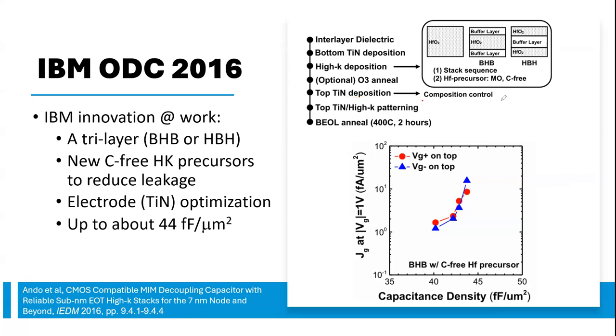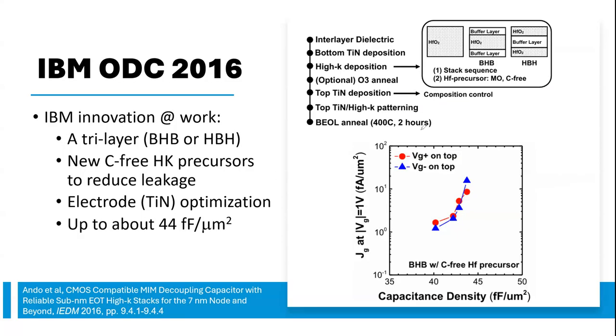Here, TiN, you have some kind of optimization. So-called top TiN deposition. And then you have patterning, the etch. And then you do a final anneal. This is a little bit long, 400 degrees Celsius, 2 hours. You just want to densify the material, right? You want to stabilize this layer. Once you deposit and pattern, you want to anneal the whole stack. The whole stack had to be annealed. And then he did an anneal at 400 degrees Celsius, 2 hours. Kind of too long to me, but that's what he suggests.